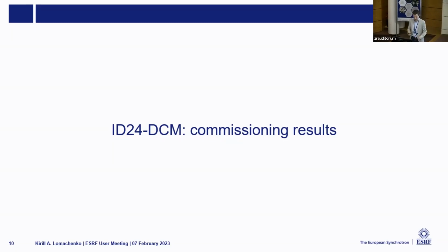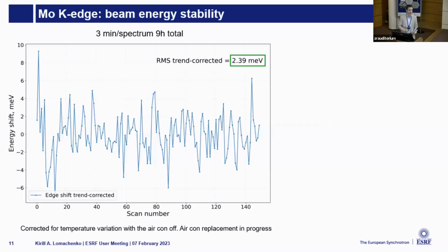When you measure XAS spectra, there are several things that you need to be sure of. The first thing is the energy stability. When you measure one spectrum, then you measure a second one, and so on, you need to be sure that they don't shift much with respect to each other. So the energy scale has to be stable. And here is the energy stability that we achieved at 20 keV, so at the molybdenum edge. We have a stability of around 2 meV.